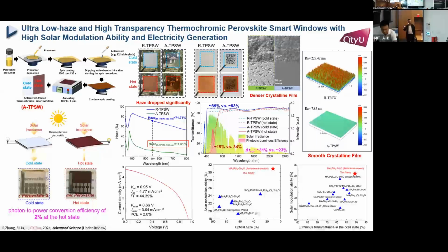It's significantly enhanced. This is the SEM photo showing the very smooth morphology of the coating after using the anti-solvent method. The surface roughness is reduced to 7 nanometers. If we do not use the anti-solvent method, the previous morphology is very rough, and the roughness is about 220 nanometers. If we do not have a very smooth surface, even with some electrolyte, the window cannot generate electricity. So that's one thing we need to solve: the morphology.